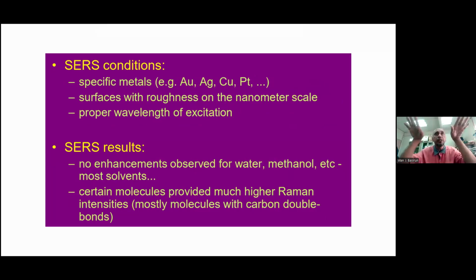You must have certain metal, for example gold, silver, platinum. The metal surface must be rough on a nanometer scale, and the proper excitation laser wavelength. So this SERS result, when we look at this SERS, the water, methanol, and most solvents do not give enhancement because they are not adsorbed onto the metal surface.